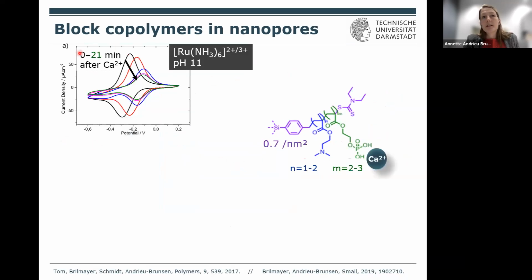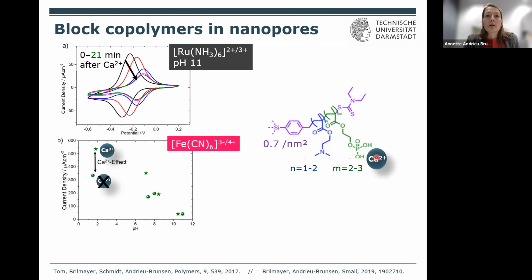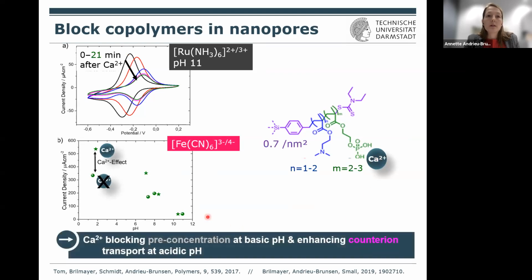And in addition, just because we had this phosphate again in the copolymer, we checked the influence of calcium as well. And what you see is that calcium is blocking pre-concentration at basic pH and enhancing counter ion transport at acidic pH. And as well, this behavior is more complex than just the combination phosphate calcium. Of course, the calcium interacts with both partners, with everything that's present in the pore.